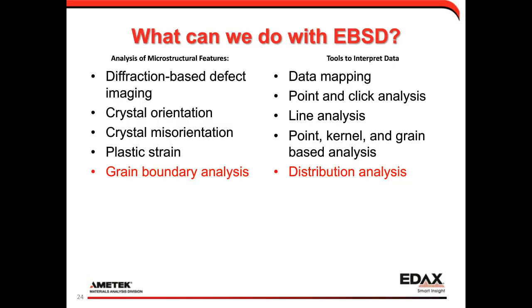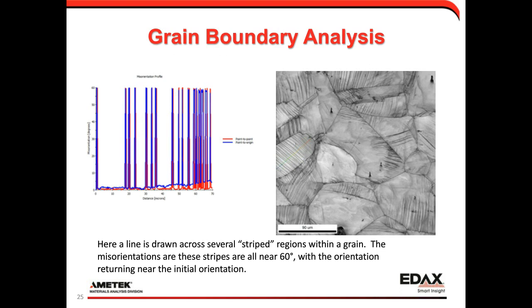And that leads to the idea of grain boundary analysis. Not every grain boundary has the same type of influence on material properties. So we're able to look and see what type of boundaries occur in a material. This is a basic way of looking at it. This is looking at one of these lined, striped areas within a grain. If we look at the misorientation that evolves there, we see there are lots of peaks near 60 degrees, and then it comes back down. So that 60 degrees is sort of a magic number.